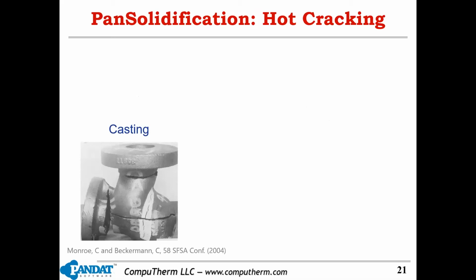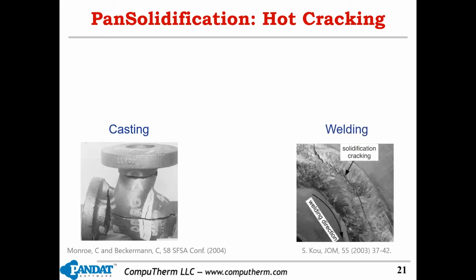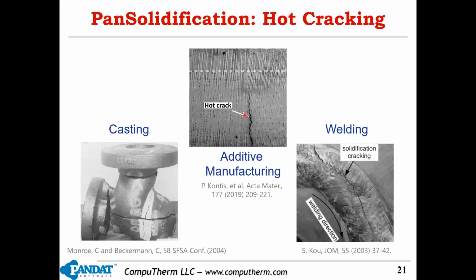So the third module for the second generation software is basically Pan solidification. The Pan solidification module focuses on simulation of the solidification process. Here, I will use an example to demonstrate how we can use it to predict hot cracking in aluminum alloys. As we all know, hot cracking is a very common defect generated during solidification of casting and welding, and even additive manufacturing. Hot cracking is a very complicated phenomenon. So many criteria have been developed in the past several decades to predict hot cracking susceptibility of alloys. So people try to avoid this kind of cracking, right?